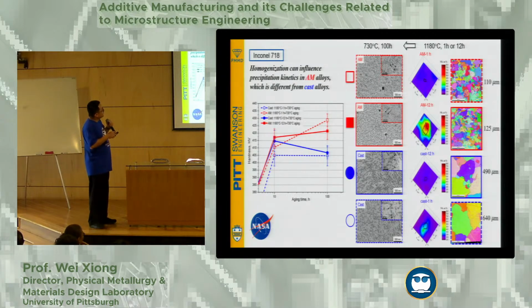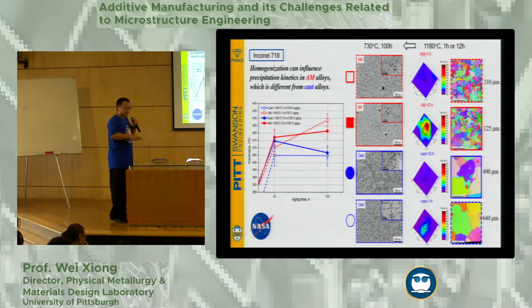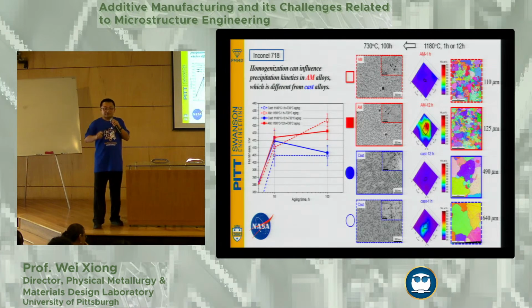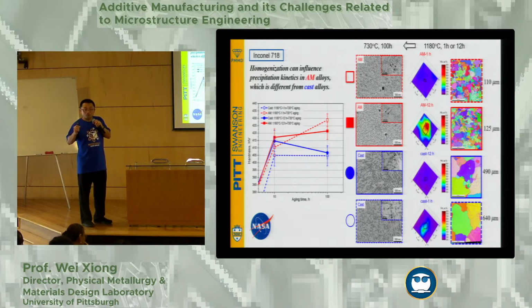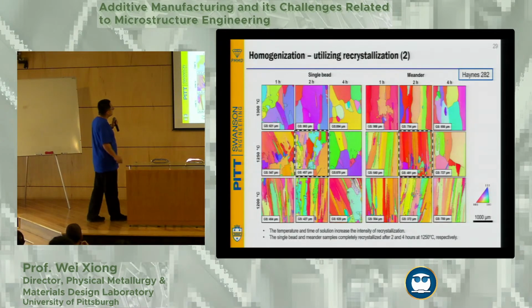If you look at this, if you do the first homogenization process, you receive fine grains. However, the consequent lower temperature aging process will introduce different precipitation behavior. That's because the homogeneity of niobium, the most important element in this alloy contributing to formation of gamma prime and gamma double prime, is actually different now. So you can no longer use the traditional cast alloy heat treatment. You have to further change the heat treatment schedule to ensure you keep the same or even higher strength than the traditional material. That's the piece of information we have to keep in mind.